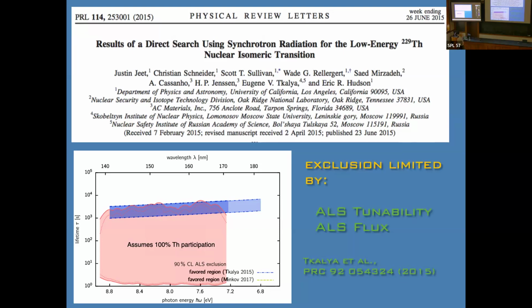This exclusion was limited by two things. One is tunability. Despite being a synchrotron, we weren't allowed to tune it above 170 nanometers. And then even though there's a lot of photons in these synchrotrons, the spectral radiance is small because the bandwidth is very large. So we're limited by flux in a spectral sense.